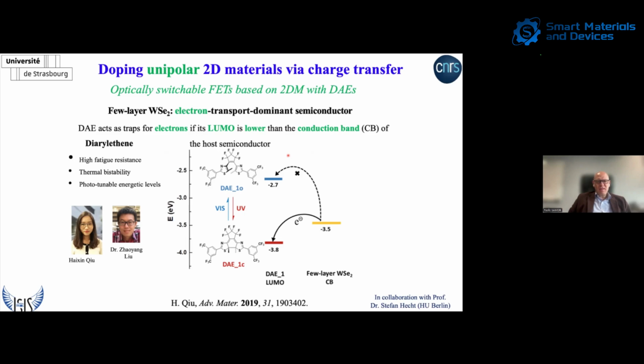Now, here we focus on tungsten diselenide, and we chose this because it's unique. Depending on the thickness, it can act either as an electron transporting material or as an ambipolar material. So in the first example I will show you, we treated tungsten diselenide in a thickness that was an electron transport material. Later we will see how it can also be used as ambipolar. And here we combine this with diarylethene. Diarylethene has the peculiarity of having high fatigue resistance, thermal bistability, and phototunable energy levels.